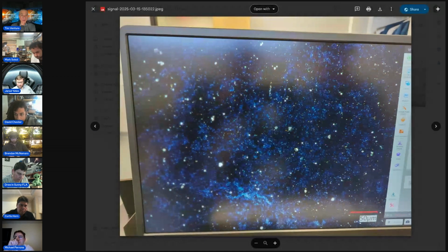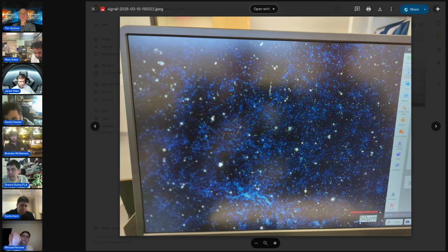There's one more thing I forgot to mention. We took some SEM from the side and the top, though we didn't get pictures of it yet. We basically took the XY plane, the YZ plane, and the other, looking for anisotropic crystal structure, because 7000 series aluminum is sometimes like a wrought alloy, and basically if you squish the material, then the aluminum silicide, if you really squish it, the crystals will sort of align along a specific dimension, and you'll be able to tell that it was mechanically deformed and worked. But we don't have enough data to suggest that it is yet. If it was deformed that way, it wasn't by a large amount.